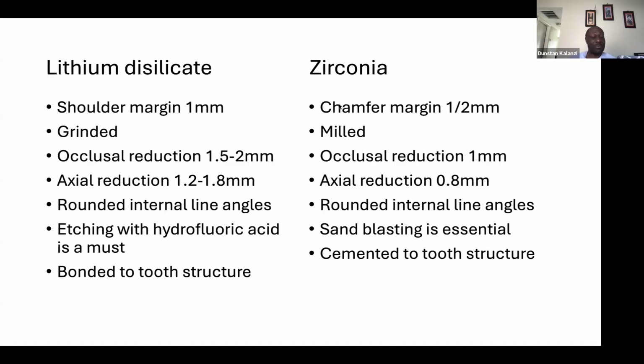There's a difference in the processes of cementation of these crowns. It is more systematic with your glass ceramics as opposed to your zirconia. Zirconia just requires sandblasting of the fitting surface, and then you can cement. So it's cemented to the tooth structure. The silicates are normally bonded to the tooth structure. So you have your resin, your etchant, the silane, the primer, and then you use the resin cement.